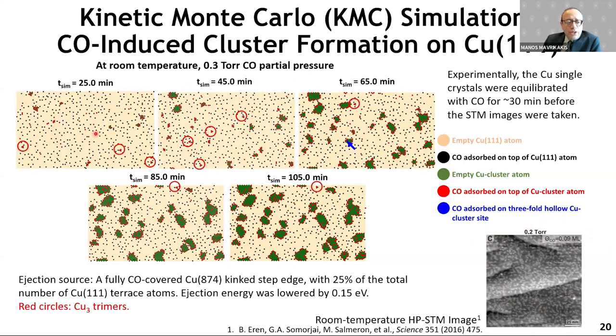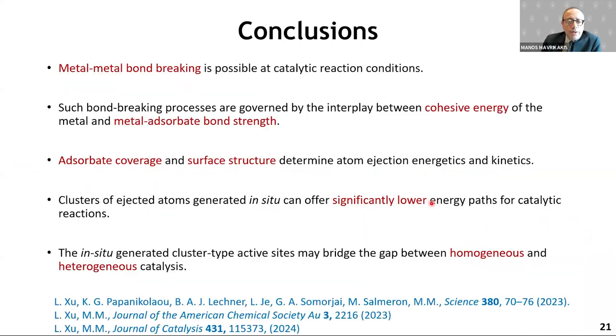And you can see you start with atoms, you generate more and more of these, start agglomerating, making bigger and bigger clusters. But these red circles indicate trimers. It turns out that these trimers persist. They are not that many, but they can still dominate chemistry at conditions relevant to what was reported by the Berkeley groups a few years back.